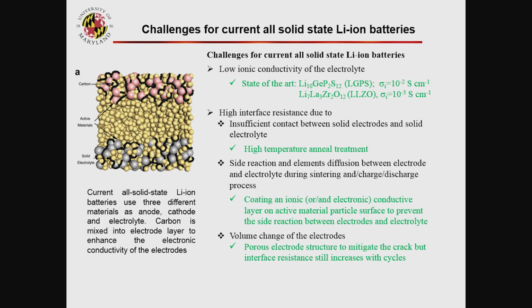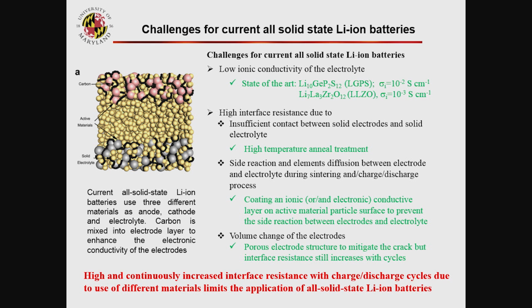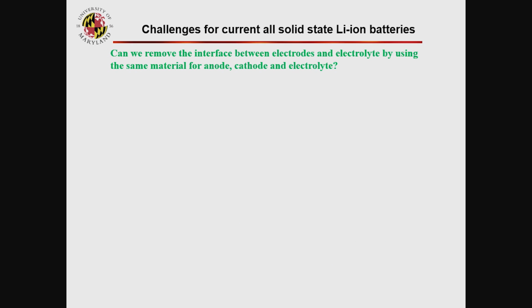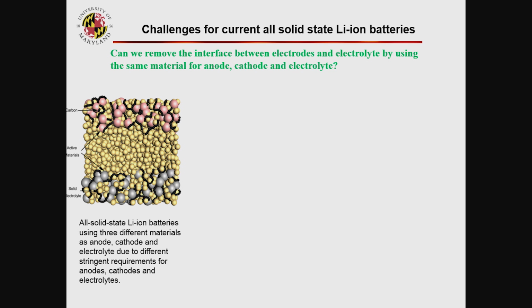Because once one active material particle changes volume, the interface resistance continues to increase. So the idea, if you really want to remove the interface, is: is there any way that electrode and electrolytes are one material, so we do not have an interface? Because the interface is really a challenge right now. If we can remove the interface by using a single material, maybe we can reduce the continuous increase of the interface resistance. So we want to check whether it's possible or not.